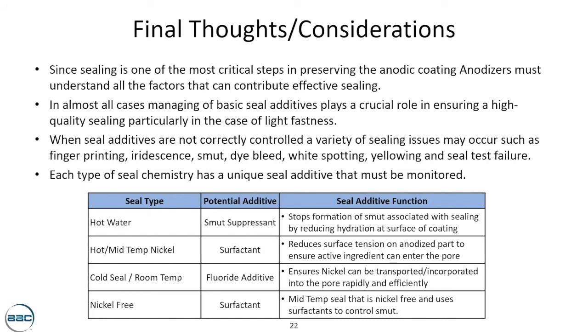For the hot water seal, the smut suppressant stops the formation of smut associated with the sealing by reducing the hydration at the surface of the coating. For the hot or mid-temperature seal, the surfactant used in the seal is pretty important, which reduces the surface tension of the anodized part to ensure the active ingredient can enter the pore. For the cold seal or the room temperature seal, the fluoride content is pretty important to maintain, which ensures that the nickel can be incorporated or transported into the pore rapidly and efficiently. For the nickel-free seal, again, the surfactant is very important, and for the mid-temp seal, that is nickel-free and uses surfactants to control smut.